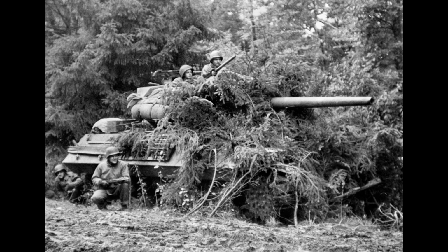The inconsistent hardness created vulnerabilities that American tankers learned to exploit. Areas of softer armor, typically near welds or at plate edges where heat treatment effects were less uniform, became preferred aiming points for experienced crews. Sherman gunners trained to target these areas, achieving penetrations against armor that should have been proof against their guns if hardness had been uniform throughout.